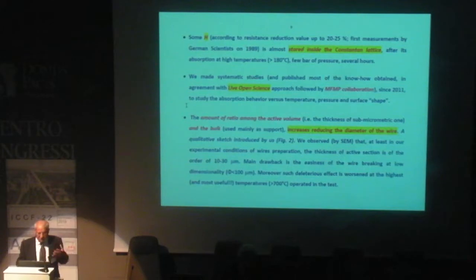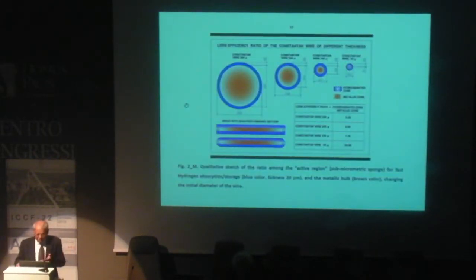At a point, we observed that the thinner the wire, the better the results. So a simple explanation is just geometry. Because the thickness of the sponge is almost constant, 10, 20 micron, the ratio between the bulk, with very low activity, and the surface increases by reducing the wire diameter. Quite simple explanation.